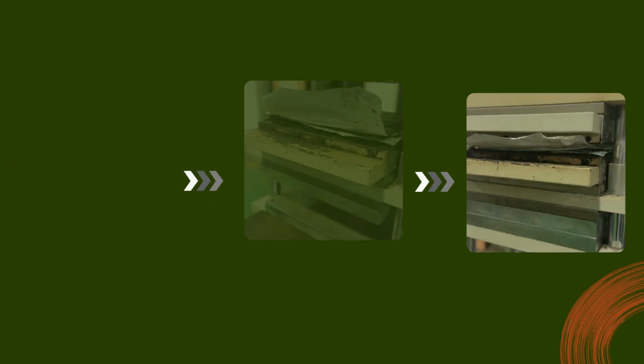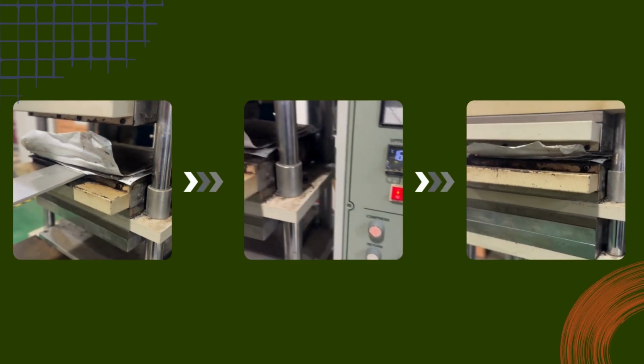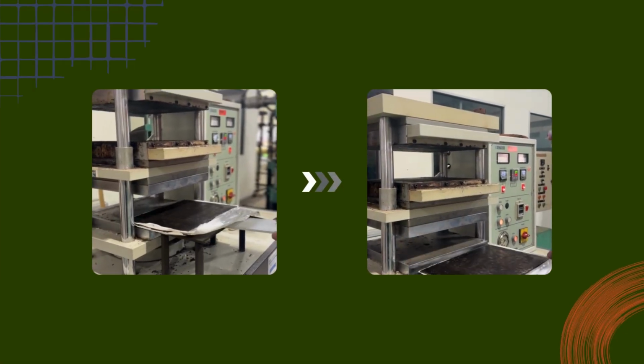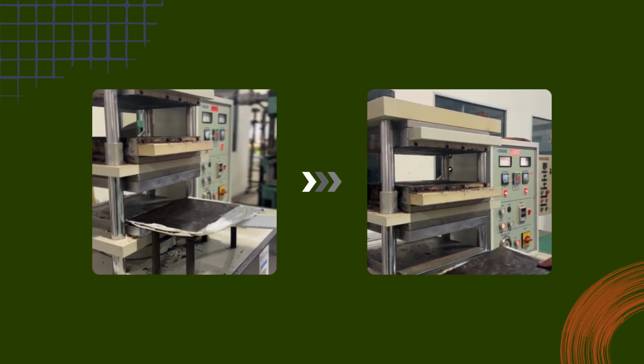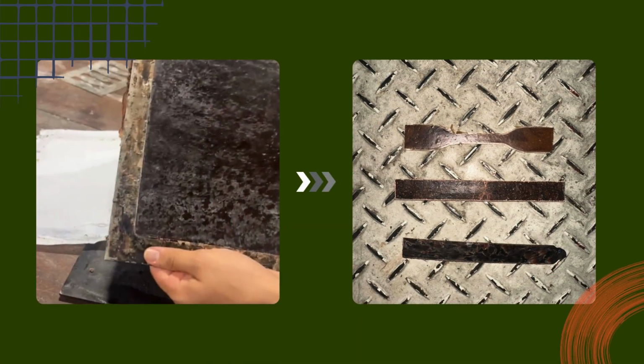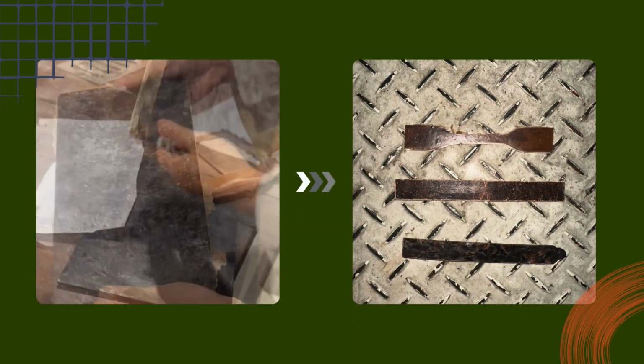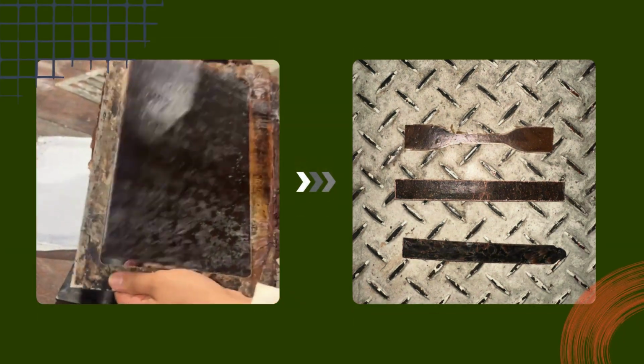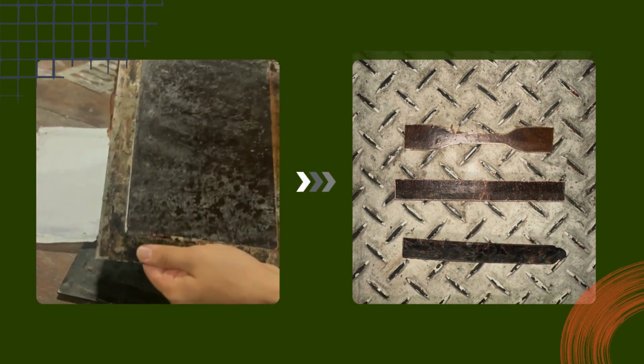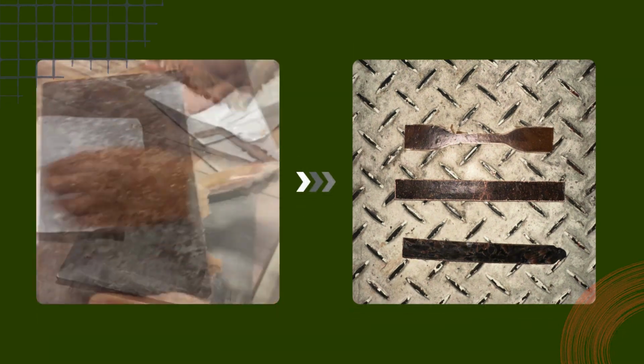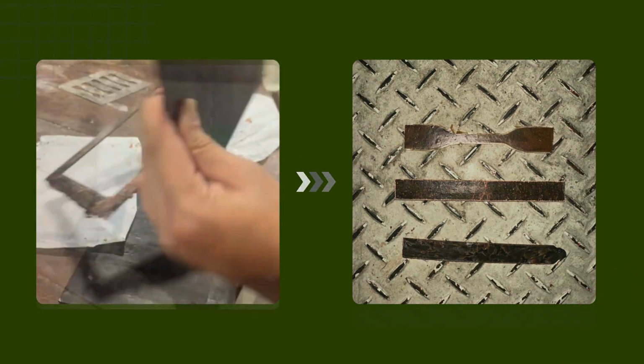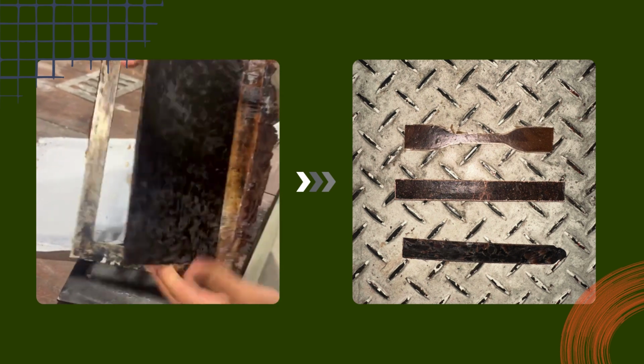After sufficient heating, we held the sample under pressure for a few minutes to ensure good bonding between the particles. Finally, the sample was cooled by transferring it back onto the cold plate, where it was repressed to solidify the material and complete the molding process. After the cooling process, the sample is carefully removed from the mold and trimmed to meet the exact dimensions specified by ASTM standards for the flexural and flammability tests. For the tensile test, the process is repeated using a specific mold designed to produce tensile test samples. This ensures that the samples are properly shaped and sized according to ASTM requirements, allowing accurate and consistent testing across